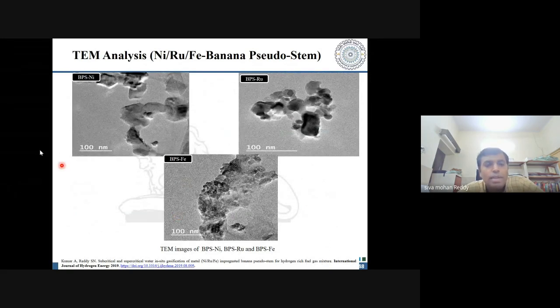So if you look at the TEM profile over here, we see that the particle size is going to be less than 100 nanometers, which conveys that the metals embedded in your biomass matrix form a nanometal composite of carbon, where the metals are in the size range of less than 100 nanometers and are encapsulated in the biomass matrix. This is your nickel one, this is your ruthenium, and this is your iron one.